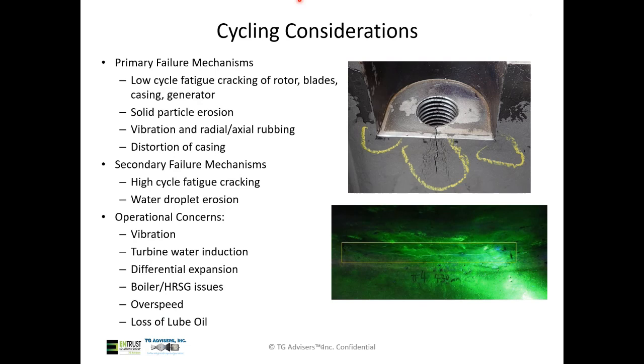What I'm showing on the right side of the screen is just some examples of cracks that have developed in units. Both of these are casing cracks that have developed from cyclic operation. So quite a bit of on-off cycles. You can see these are stress concentrations from the threads in this bolt hole or from this corner. And wherever we've got a stress concentration, these cracks initiate following these repeated stress cycles.